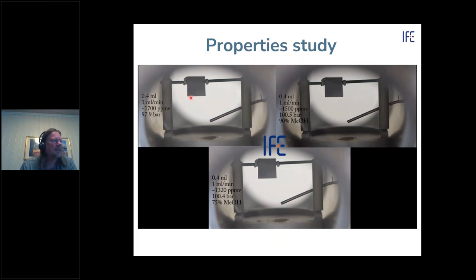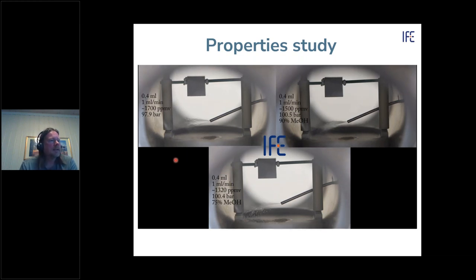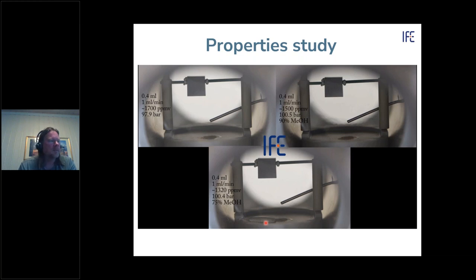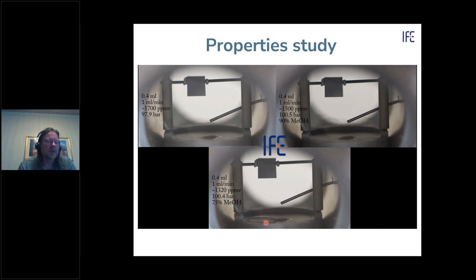We also studied methanol solubility in CO2 at three concentrations: 100%, 90%, and 75% methanol. Using thermodynamic models and solubility charts, we found that methanol at 100% and 90% is fully miscible in CO2 and dissolves completely, while at 75% methanol a pool of methanol-water mix remains. This is practically useful for pipeline commissioning — methanol appears to be the best choice to push water out.